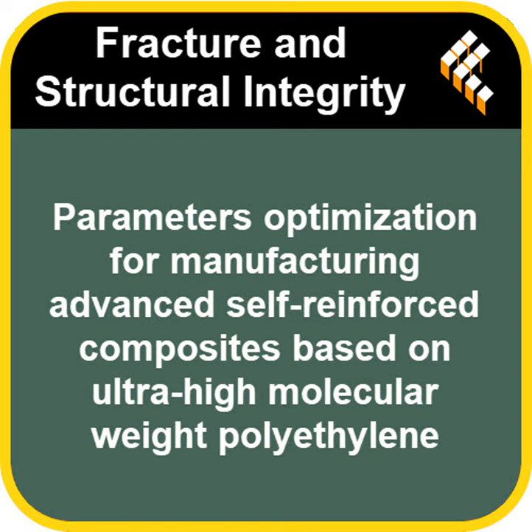What happened at the very top end, 180 degrees? See, there things changed. At 180 C, the samples didn't really fail by shearing apart cleanly anymore. They just sort of deformed plastically like a solid block of polymer. They lost that layered behavior. Meaning the heat was too much.